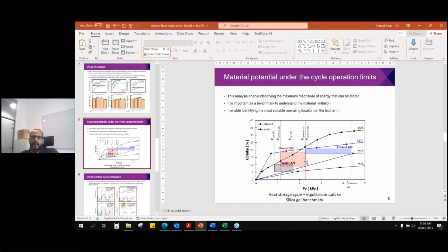We can see that we have bigger size of cycles, so the net cyclic uptake potential for the ethanol is very high. If I have high heat absorption, it would be happy days. So high heat absorption, high uptake, it means that I have high heat can be stored between seasons. If I have here actually low uptake, so yeah, we have high heat absorption, but the uptake is very small between this operating condition, between these limits.